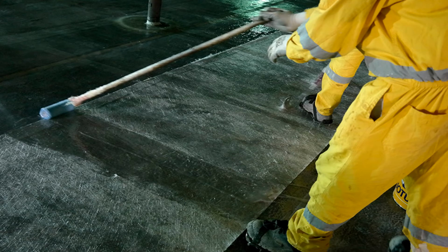Even if severe corrosion is present on the outside, it is possible to apply a double layer of the laminate for a total thickness of 110 to 120 mils. Linings of less than 20 mils dry film thickness will not protect against leakage from outside corrosion. They are recommended only for relatively new tanks with no internal pitting and underside corrosion.